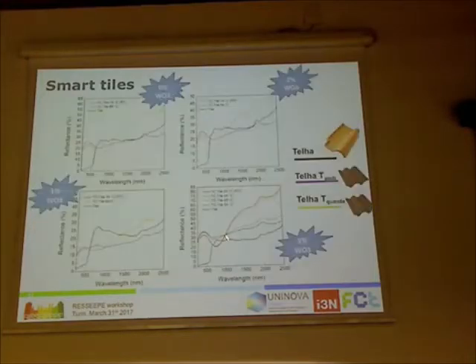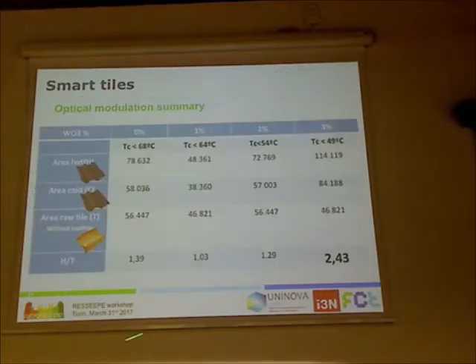If you consider the area under the curve—considering all wavelengths and the change in reflectance across them—the maximum difference between the hot coated tile above the critical temperature and the tile without any coating can be 2 times higher in total area for the coated tile. This really proves it can contribute to reducing the transmission of infrared radiation through the tile.